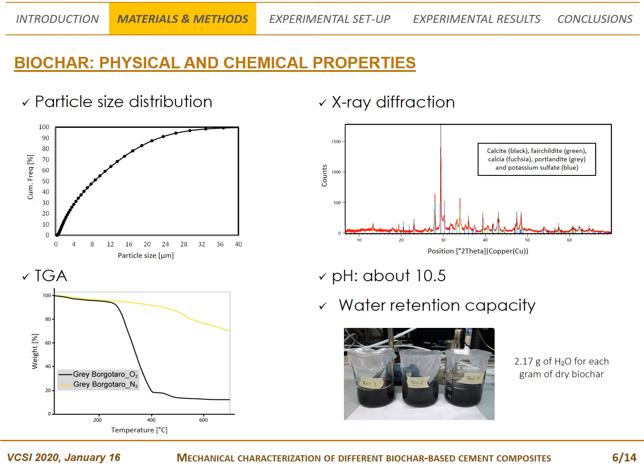First of all, it was necessary to chemically and physically characterize the adopted biochar. Particle size distribution was analyzed, resulting in a range of some micrometers. Then, biochar was analyzed by means of X-ray diffraction to have a first identification of the presence of amorphous and crystalline phases. In general, the thermostability of biochar depends on the temperature of its production process. The increase in temperature originates indeed more stable carbon forms with a high heat resistance of the material. To verify if the residual weight is due to more stable carbon forms during the gasification process, a thermogravimetric analysis was carried out under airflow. The presence of an unburned fraction could be attributed to the presence of inorganic compounds or metals.